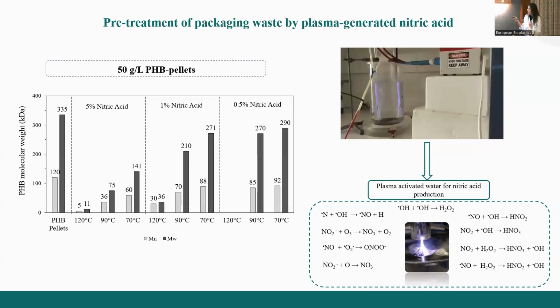So here we carried out some experiments using different concentrations of nitric acid solutions from 0.5 to 5%, and at various temperatures from 70 to 120 degrees Celsius. And the results showed that the higher the temperature, in combination with higher nitric acid concentrations, the lower the molecular weight of the pretreated PHB samples.